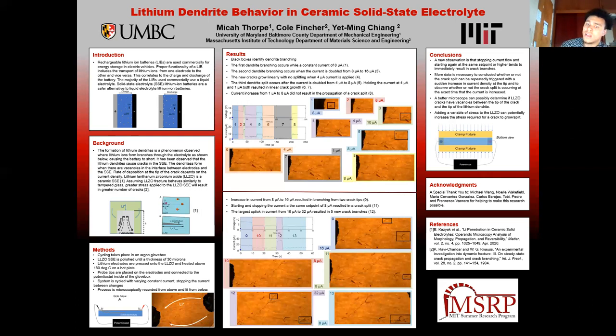Based on previous work and studies into the fracture behavior of tempered glass, you can assume that with more current applied, there's faster deposition of lithium ions on the dendrite tip, which means greater stress buildup at the surface. And if we assume that the ceramic electrolyte behaves similar to tempered glass, the greater stress that you apply to the glass, or in this case, the ceramic, the more cracks will form.